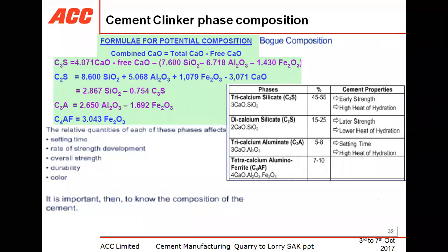So this is the Bogue composition, Bogue formula. These are the empirical formulas to calculate C3S, C2S, C3A and C4AF in clinker. This gives you a theoretical value. When you calculate C3S, if you apply this formula: 4.07 into calcium oxide minus lime, minus 7.6 into silica, minus 6.7 alumina, minus 1.43 into iron. This will give you the theoretical percentage of C3S.